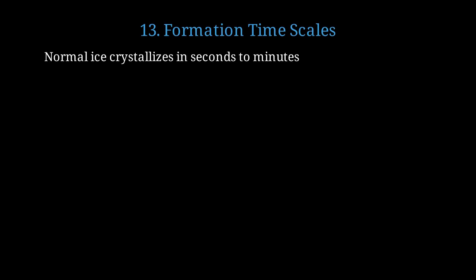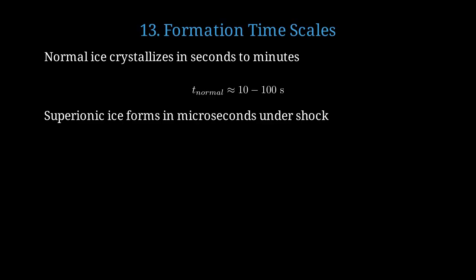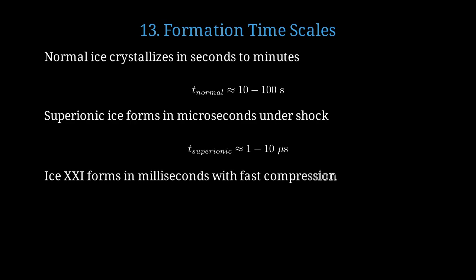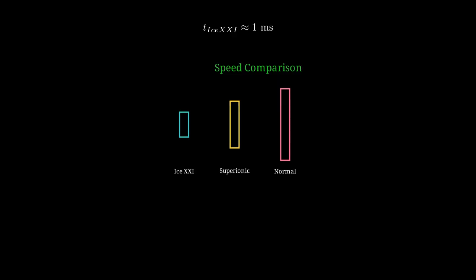The timescales for forming these exotic ices are fascinating. Normal ice takes seconds to minutes to crystallize from liquid water in your freezer. The formation time for normal ice is typically 10 to 100 seconds. But Superionic ice forms in just microseconds when subjected to shockwave compression. The formation time is 1 to 10 microseconds, which is a millionth of a second. Ice XXI forms in milliseconds with ultra-fast compression techniques. The formation happens in about 1 millisecond, or 1,000th of a second. Here's a comparison showing relative formation speeds. Ice 21 forms fastest, then Superionic ice, with normal ice being slowest.